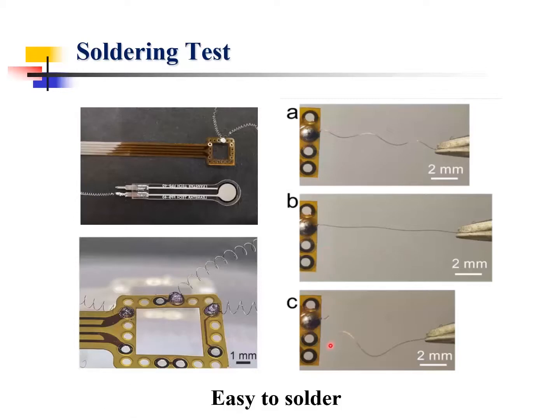Moreover, a mechanical test was conducted, and the results showed that the solder joint has strong mechanical integrity, and that the fracture occurs at the fiber, not at the joint. Compared with other solutions to join conductive fibers, such as using silver paste, the present method is mechanically robust and electrically efficient.